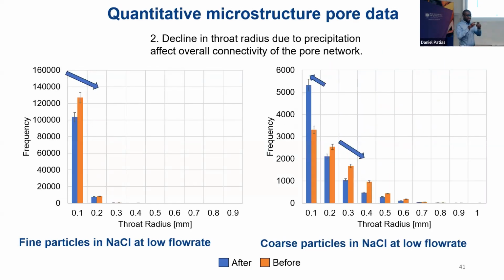For the connectivity, which is the stick between the two pores, we realized that decline in the throat radius was virtually due to precipitation, and that affects the overall connectivity of your pore system in a heap. For the fines, we have smaller throat radius, and in all cases, when the precipitate forms, it causes a decline. For the coarse materials, we have some finer throats and some larger throats. The larger throats sort of decline, but then the finer throats increase, strangely.